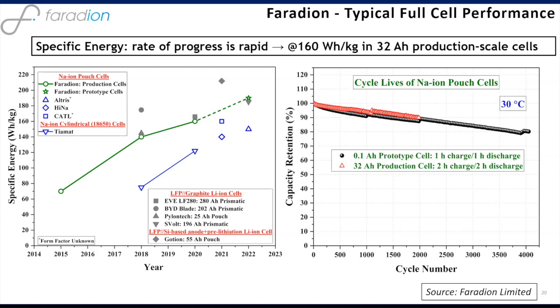On the left-hand side, I'm showing the rate of progress, in the green line, of Faradion production cells. So right now we're running at about 160 watt hours per kilogram, and the gray dots on here are comparing that with LFP graphite commercial cells from several sources. So this is a very similar performance, and that's really an extremely good performance in terms of specific energy.